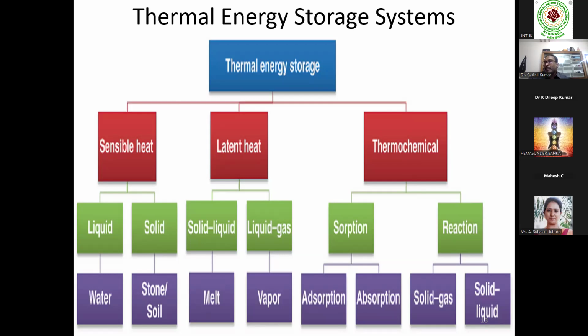The disadvantages of storing heat in a medium are that the temperature of the medium changes as thermal energy is extracted, which complicates delivery of the stored energy, and energy densities are relatively low. For example, if you have water at 50 degrees centigrade and stored energy is to be delivered at a temperature of 20 degrees centigrade, the heat capacity of water, 4200, can be multiplied with the difference between them, which gives about 0.13 megajoules per kg. The energy density is increased if a phase change in the medium is involved when the energy is stored or released.